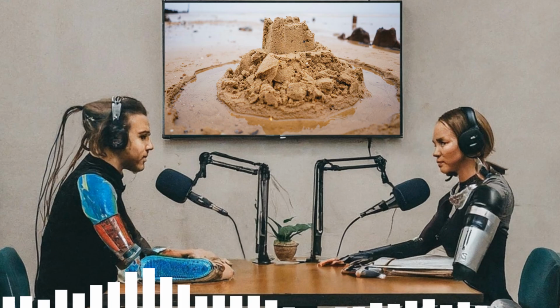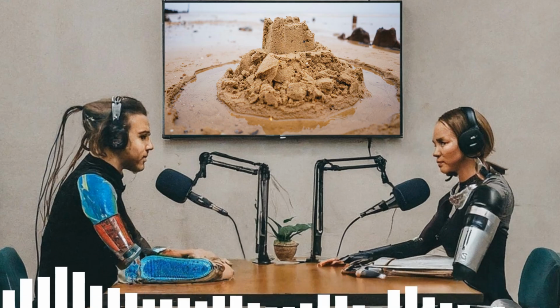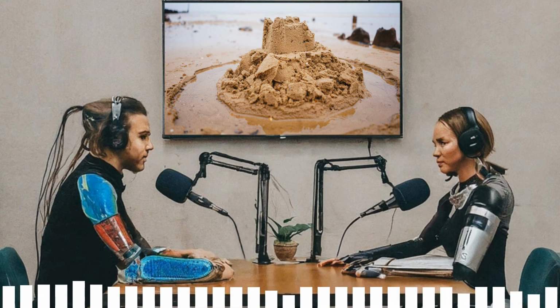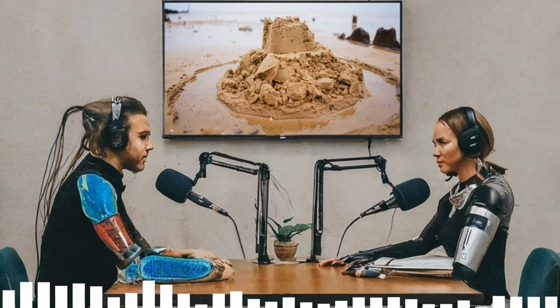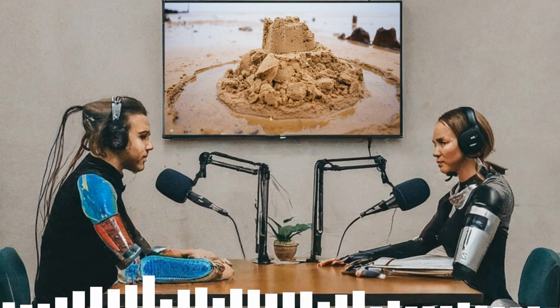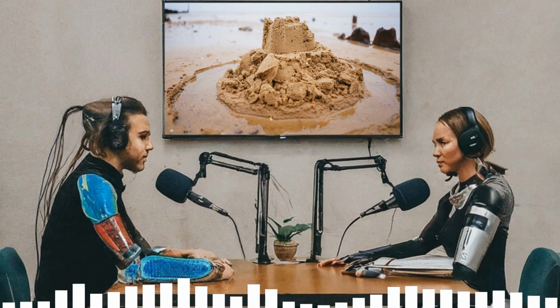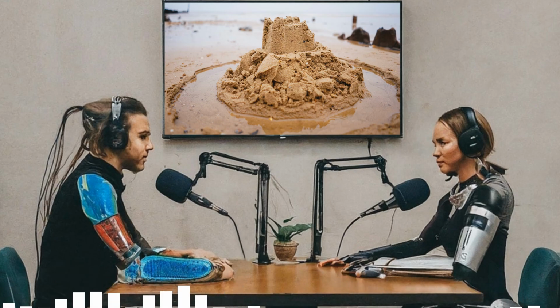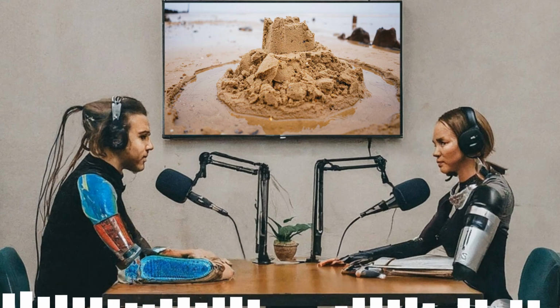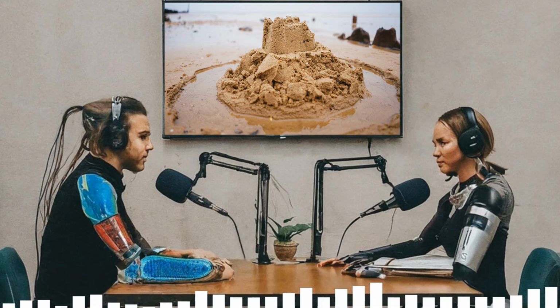It really is. And because they could measure the properties of the wet sand, specifically its elastic modulus, which is basically how stiff it is, they could actually use their theory to quantitatively predict those heights they measured, which is huge. It means we can now predict pretty accurately how high a sandcastle could be built, depending on the sand grain size and the base.